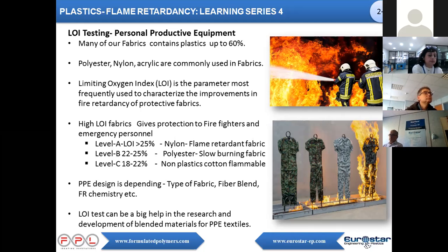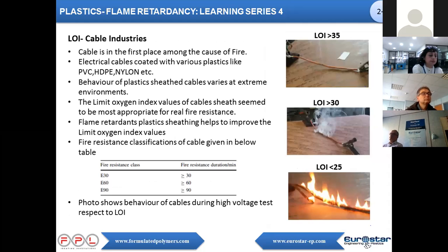Now we move on to LOI application in the cable industries. Electric wiring is part of the fire protection system. Cable firing is a major cause of electrical fires. Plastics with high LOI values like nylon, PVC and PE are normally used for cable sheathing. Plastic coated cables do not burn in normal air, but in high oxygen content and overload environments, cables behave differently. Addition of FR additive helps to improve LOI values considerably.